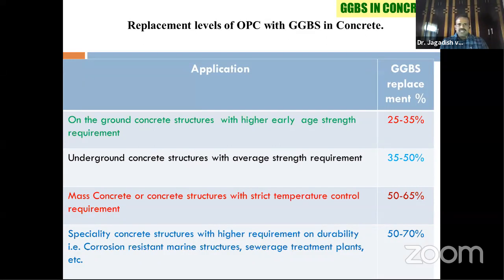Particularly for ground concrete structures, when you're aiming for higher early-age strength, one can replace up to 25 to 35%. Underground structures have an aggressive environment, and the soil is corrosive. Due to soil, it may corrode. So one can go to 35 to 50%.